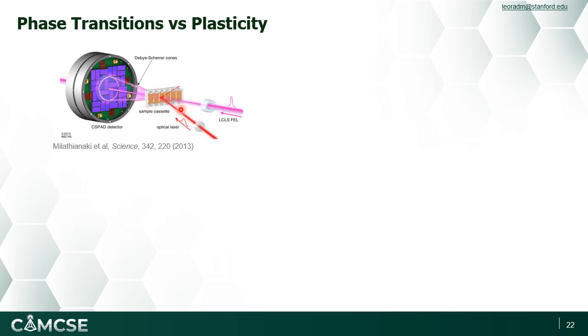So the optical laser pumps the material, generating a shock wave that is then probed at some delay time later by the LCLS free electron laser beam, i.e. our X-ray pulse that is so short in time that it allows us to directly watch the positions of the atoms as the process is evolving.